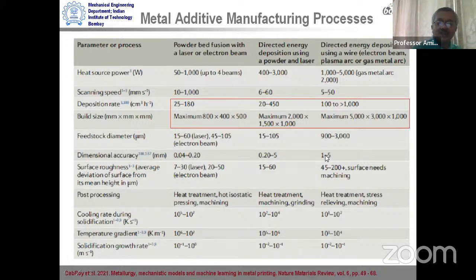So I think basically the difference between DED and PBF processes is in the way you can consider the feedstock material in your model. In DED, your feedstock material is coming through the heat source, so there would be a certain temperature of the feedstock material when it meets the melt pool on the substrate or on the already solidified surface. In contrast, in a powder bed process, the powder is already laid on the bed, so the laser is directly irradiating the powder. So that's one challenge to take care of. The second challenge, of course, is the scale.